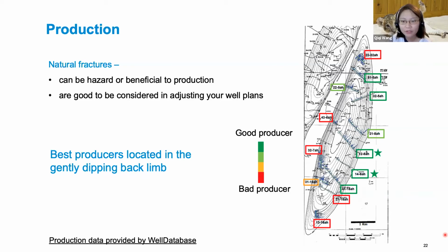And we can gain more proof from looking at the production. So I look at the cumulative barrel of oil equivalent, cumulative BOE, the production lifespan, and the total water production in each studied well. On the map, I have good producers in green and bad producers in red. So we see a definitive production difference between wells in the same anticline. We have 60% of the production coming from the top 20% producers, where the cumulative BOE of good producers can be up to 5 times that of a bad producer.